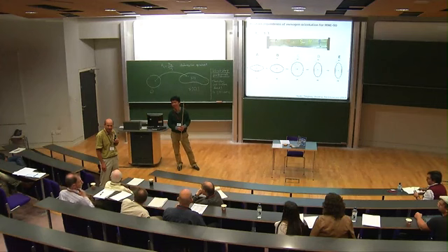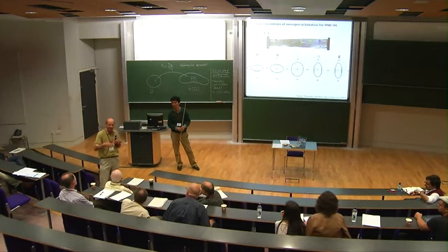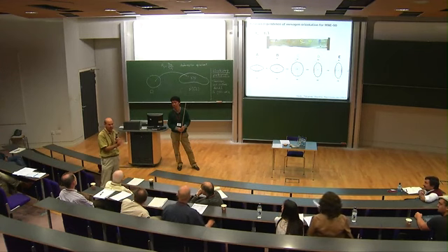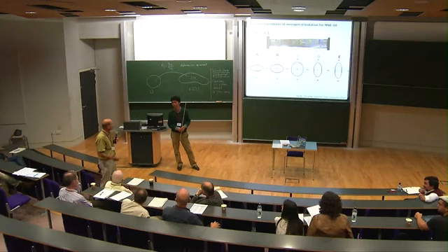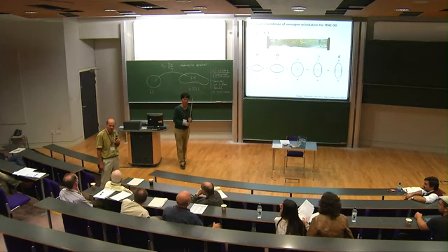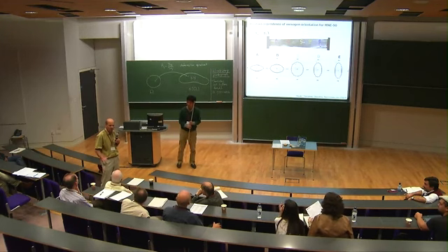I'm not sure that everybody in the audience is actually aware just how anomalous and strange this result is. The dielectric anisotropy is positive? It doesn't matter whether it's positive or negative. It should always get thicker, and therefore thinner in the plane. The oil is not miscible with the rubber, is it? Everything we've reached for to try and explain this, we've failed completely.